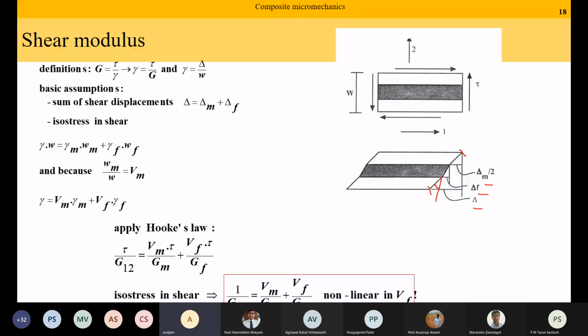So in other words, we are saying that if I apply shear stress to a unidirectional composite, then the composite material is showing me isostress. Isostress means that the stress in the fiber and the matrix is the same. And then in exactly the same identical manner as we have calculated the longitudinal modulus, we did everything exactly the same, other than the fact that we use shear strain and shear stress, we find out that the shear modulus is also non-linear in fiber volume fraction. It is inverse rule of mixtures.